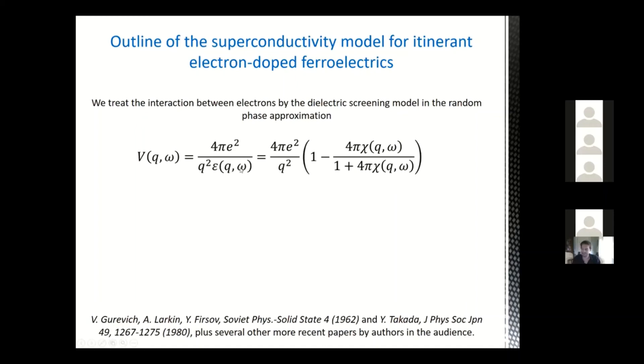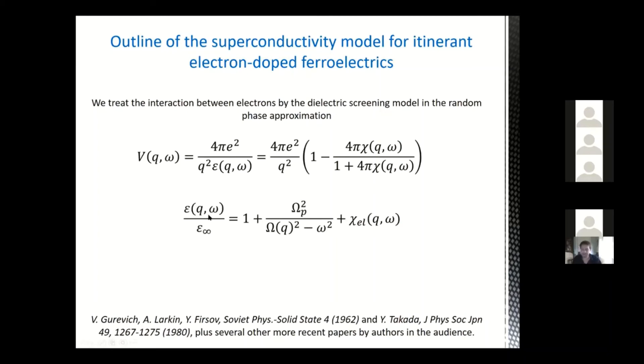We can also see the well-known dome of superconductivity as a function of carrier density, with optimal doping around 10¹⁹ to 10²⁰ carriers per cubic centimeter. Niobium-doped samples are only superconducting in this range and not below 10¹⁸ carriers per cubic centimeter. We selected the dielectric screening model within the random phase approximation, building on foundational work of Gurevich, Larkin, Firsov from the 1960s, and Takada from the 1980s. The interaction between two electrons in a doped dielectric depends on the wave vector and frequency dependent dielectric function epsilon. It comprises a direct Coulomb repulsion between electrons and an attractive term involving the dielectric susceptibility chi.